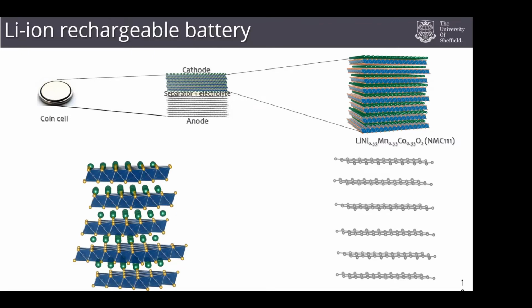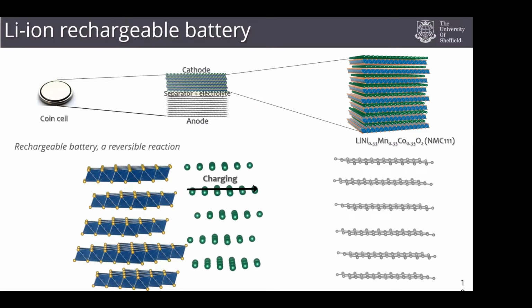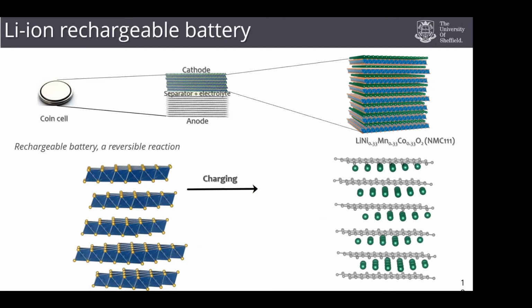And then your cathode has some redox reaction. And at the same time that those electrons are moving in that external circuit, you've got lithium ions moving in the opposite direction. So you've got these lithium ions that are between these metal-oxygen layers in your cathode. And during charge, those lithium ions are transported across that electrolyte, and they sit between the layers of the anode. In this case, the anode is graphite. These are just layers of carbon atoms in between which the lithium ions reside.